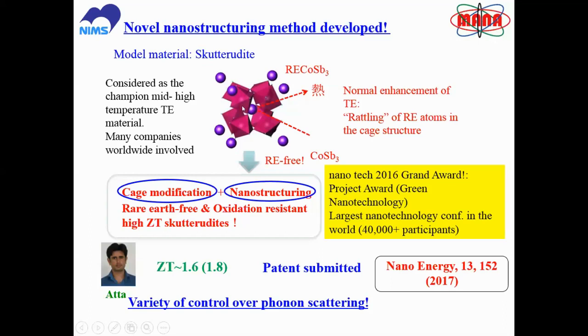So you had some scattering mechanism, but the rare earth is not so attractive because strategically, it's very localized in the world. So this is not so good, and so we want to do rare earth free. But if you don't have this atom blocking the heat, you don't get such high performance. So we try to get it with different kinds of nanostructuring.